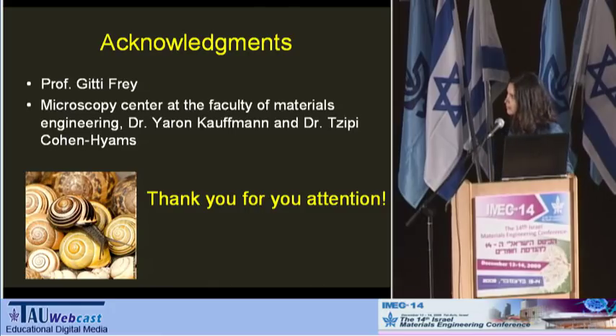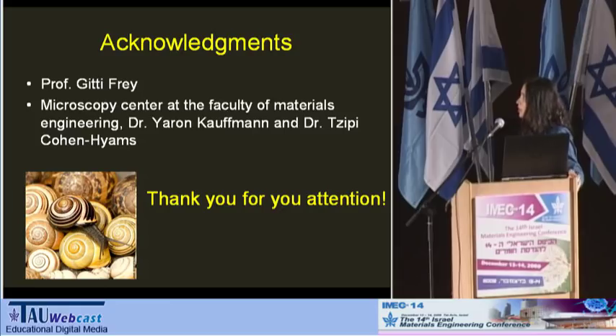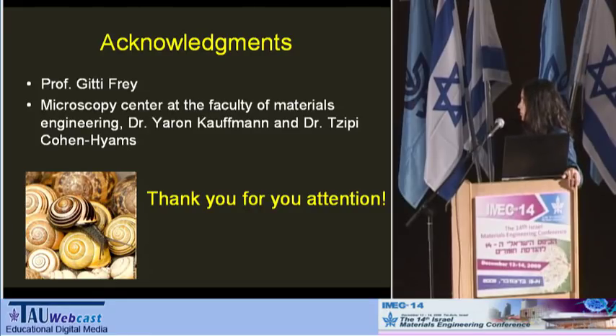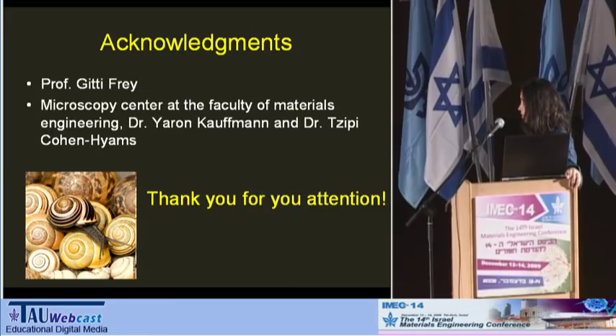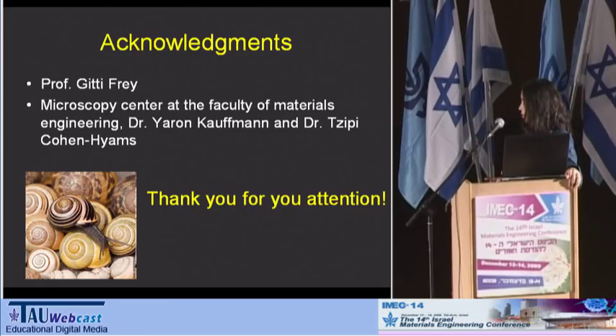Audience question: Abigail, how much water do you have inside the structure? Do you know how much uptake of solvent you have there? Response: If I have to estimate by molar ratio to the TEOS — to the silica precursor — I would say it's about a 1 to 5 molar ratio of water molecules to TEOS molecules. Question: Can you get rid of the water and still preserve the structure? Response: I need the water to be able to self-assemble the surfactants, because this is the driving force of the self-assembly — the difference between the hydrophilic parts and the hydrophobic parts of the surfactant. So this must be maintained. If you extract the water, the whole structure will not be formed.